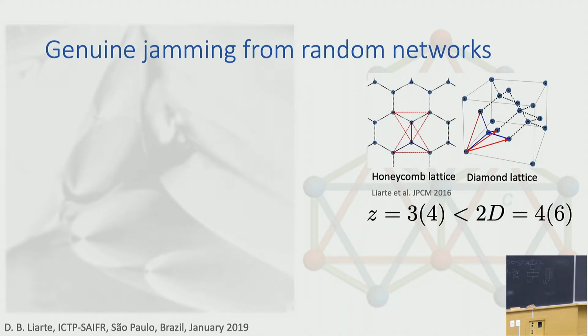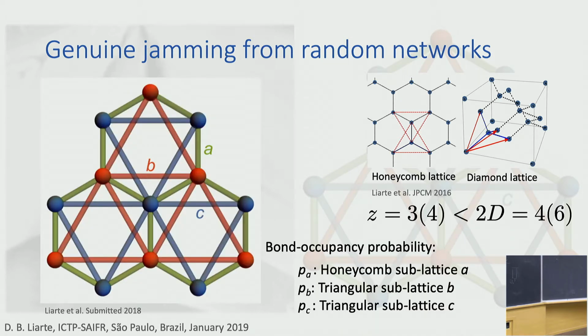And the kind of lattices that give these properties are these under-coordinated lattices. Here you have, for instance, the honeycomb lattice and the diamond lattice. The honeycomb has 3 contacts per site, whereas the diamond lattice has 4 contacts per site. They are below the limit of connectivity that you need to have mechanical stability, so they are under-coordinated. Now, the model that we consider that gives a genuine description of this jamming transition is a model where you have 3 sublattices, and that's what I'm showing here. You have a honeycomb lattice here shown by these green bonds, and each of these bonds is populated